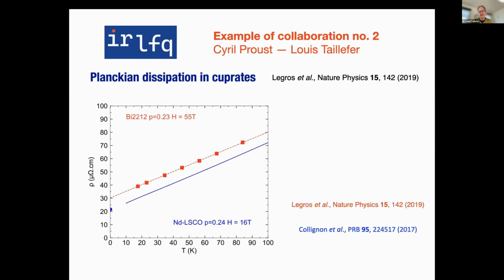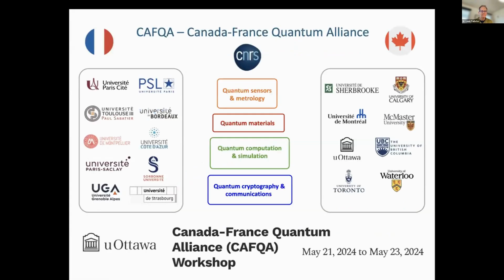Another application of these high fields is to suppress superconductivity so that we can track the resistivity down to very low temperature, as we did here in a field of 55 Tesla. And lo and behold, we find this perfectly linear temperature dependence of the so-called strange metals. So this is Planckian dissipation.